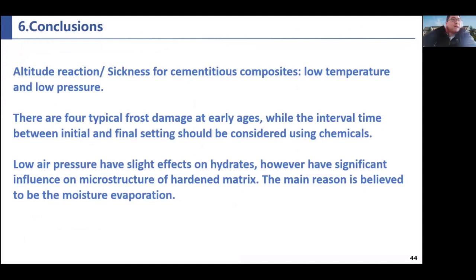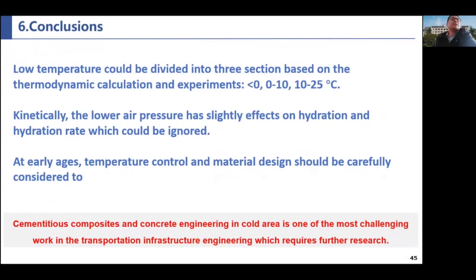Conclusions: based on our study, we know that the altitude effect on the cementitious composites includes the lower temperature effect and the lower pressure effect. And also there are 4 typical frost damages at early ages, and the lower air pressure has slight effects on the hydrates, but it has a significant influence on the microstructure of the hardened matrix. The main reason is believed to be the moisture evaporation. And also the lower temperature could be divided into 3 sections based on the thermodynamic calculation and the experiments.